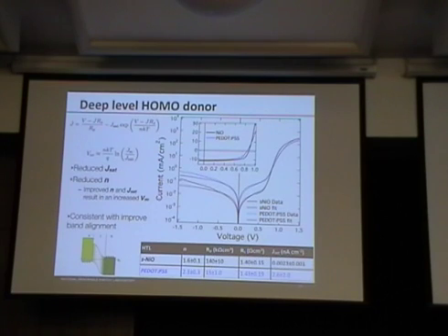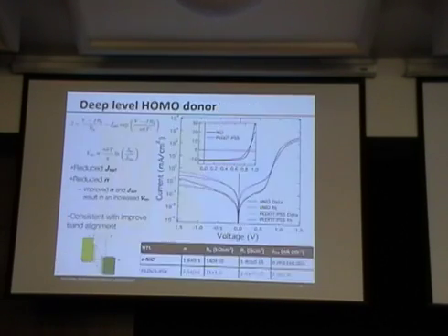But, okay, let's face it, we're plus or minus 0.3, right? It could be 2. And we clearly see that when we use the nickel oxide, we actually reduce that, so we get closer to a more ideal diode. I won't go into the details of what one can read about n, because I'm not entirely sure whether I'm right. Okay? So all of this, I would contend, is consistent with the notion that we've improved the energetics in the way that I told you.